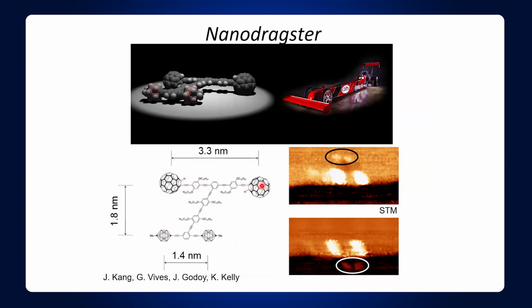And so you see they have these wheels, the big ones on back. And so this is a step edge. So sometimes along the gold, it'll go up one step. Remember we saw those gold islands? Sometimes you have a whole step edge. So it goes up and a whole new terrace now. And so this dragster is actually straddling the terrace. So it's across a terrace.